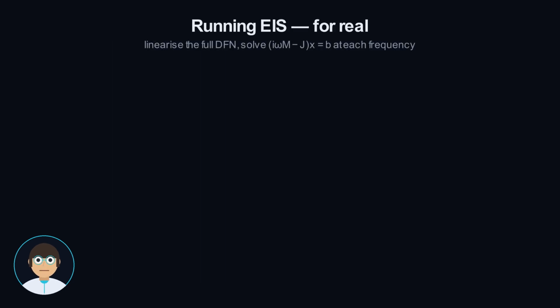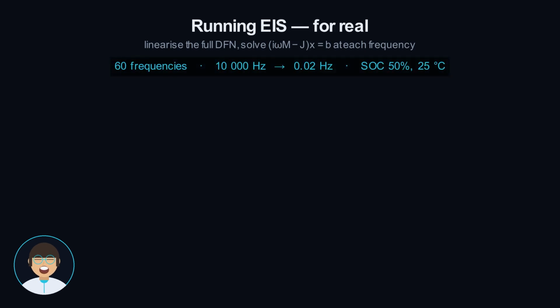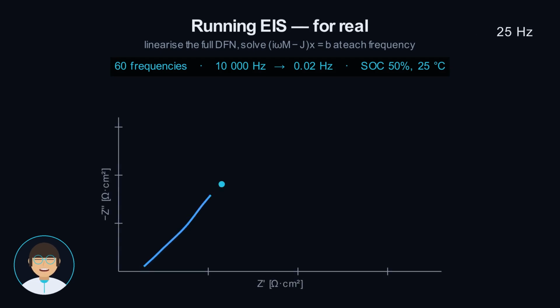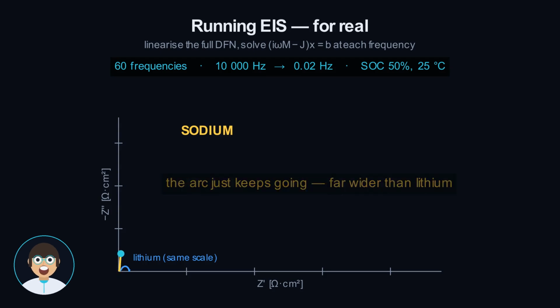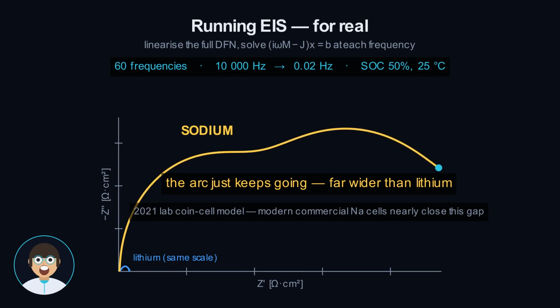Now we run it for real. Inside, the solver takes each model, linearizes the full physics around a half-charged resting point, and solves it at 60 frequencies, from 10,000 wiggles a second all the way down to 1 every 50 seconds. This is real computation, not a cartoon. Watch lithium first. The curve starts at its ohmic resistance, sweeps up into a tidy little semicircle as the chemistry kicks in, then tips into a short diffusion tail. Clean, compact. Now sodium, same start, and then the arc just keeps going. It balloons outward, far wider than lithium, before its own tail finally lifts away.